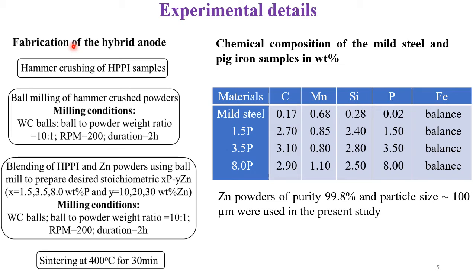So these are the experimental details which show how we have fabricated the hybrid anode. We have hammer crushed the HPPI samples, that is the pig iron samples, which could easily be done since they are highly brittle in nature, and then further decreased the size using ball milling, and then we have incorporated zinc in different weight percent, further ball milled it, and then sintered at 400 degrees centigrade for 30 minutes. So these are the compositions of the different pig iron samples which we have used, and zinc powder of 99.8% purity and around 100 micron was used.